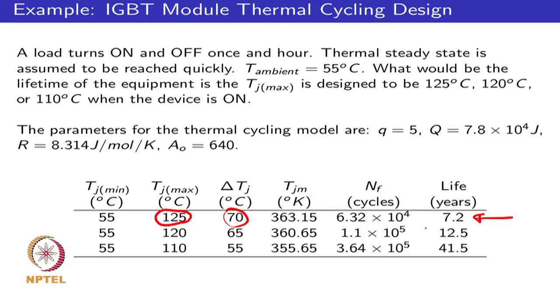So say you have an equipment which is intended to last for 10 years, then definitely this may not be a good way to do the design. You might have to select a different temperature. And one way of doing that is by going for a higher rated current rating of the device, which would typically have a lower on-state resistance with lower power dissipation. Also, your higher current rated device would have lower thermal impedance, resulting in a lower TJ max. You can get an improvement in your cycle lifetime.